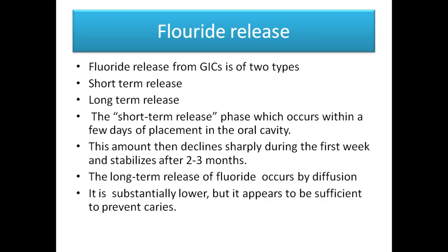During the short-term release, which occurs for about the first week, there will be an increased amount of fluoride release after the first few days after placement in the oral cavity, and it declines sharply, which stabilizes after 2 to 3 months. Afterwards, the long-term fluoride release will occur by diffusion through the restorative material.